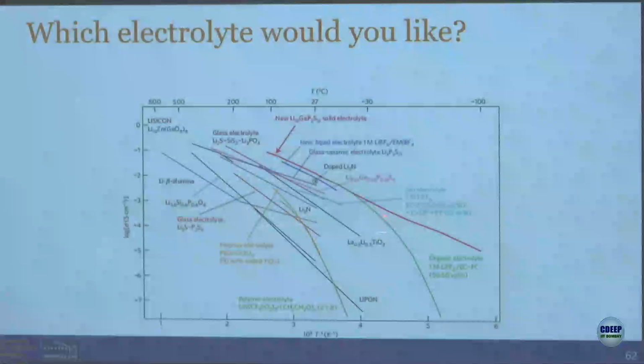Right? He showed a plot of conductivity versus temperature. He has a whole bunch of electrolytes, including this new electrolyte, the lithium germanium phosphorus sulfur electrolyte, which has this conductivity curve. You can see it's higher than everything.